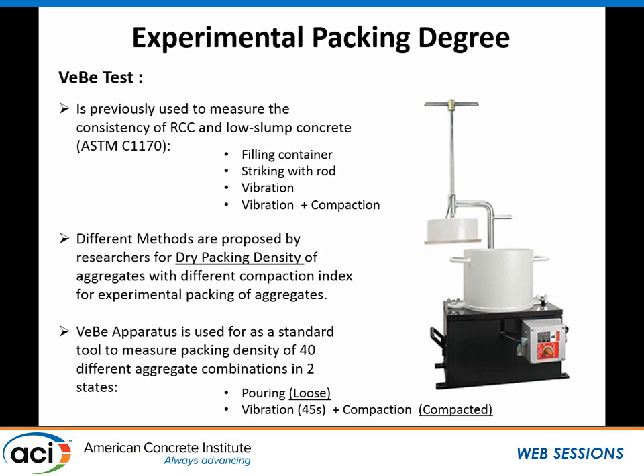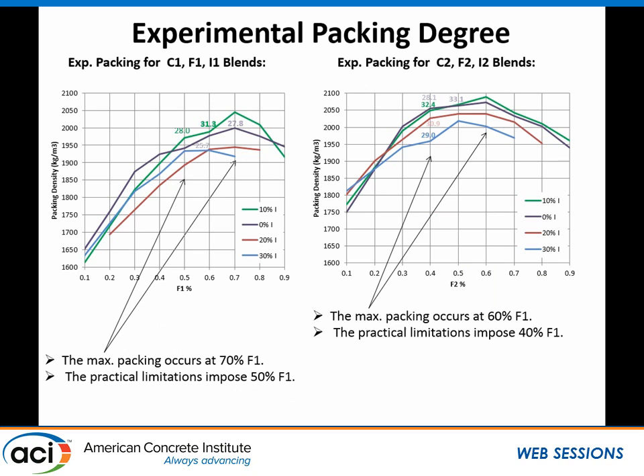So if you take the VeBe machine, which is used for finding the consistency of RCC pavements, and use that for packing, you can compare loose packing, which is before compacting, and compacted packing, and find out if loose packing and compacted packing have different influence on concrete or not. So the method used is just pouring at any combination we've had, which is called loose packing, and then vibrating for 45 seconds and compaction. We found this to be the most consistent time to pack the aggregate.